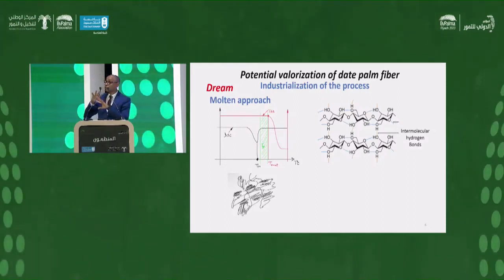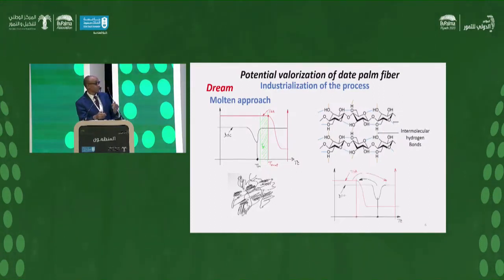But we have the 3D cross-linking of the chains. It's difficult. The density of the hydrogen bonds is much higher than the density of the bonds inside the chain. It's for that reason we have the degradation. The onset degradation is before the displacement of the linear chain. So we cannot use the molten approach because the material is degraded.